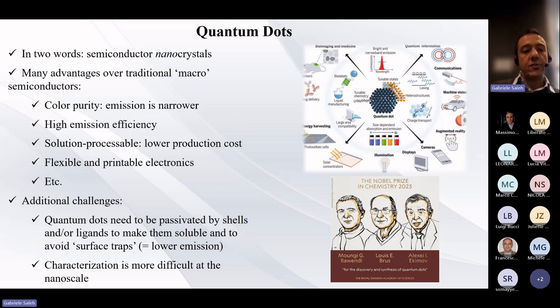However, they present some challenges, mostly the fact that, since surfaces are more important because we are at the nanoscale, on the surface we can have defects and traps that quench the emission of light, and this is detrimental for the application in which we need them to emit light. And there are a bunch of strategies to deal with this, some of which Juliette mentioned. Mostly we use ligands to passivate the surface traps. Also, they are more challenging to characterize, but this is less important at the moment.